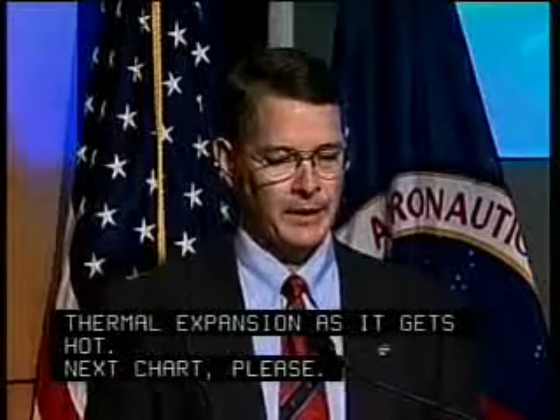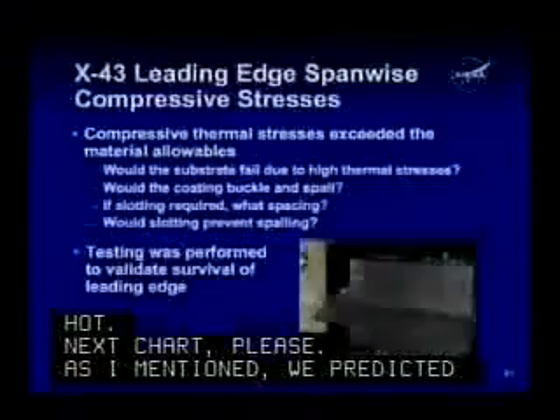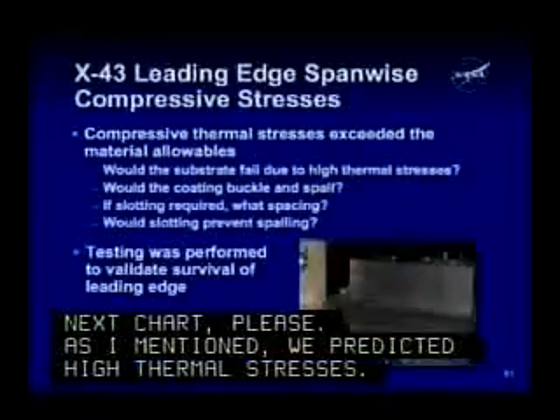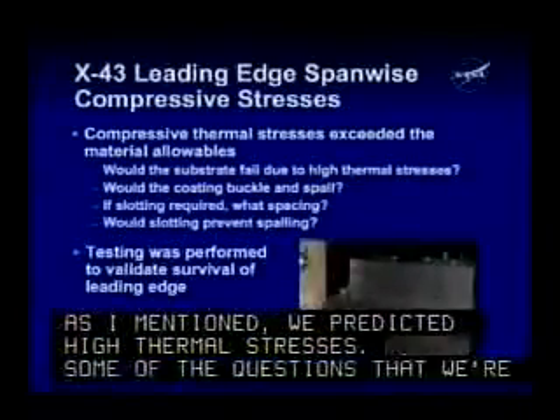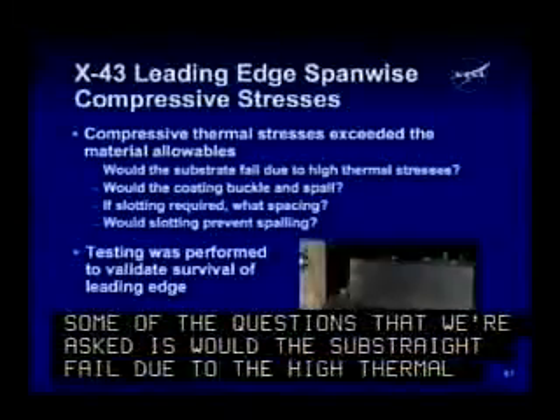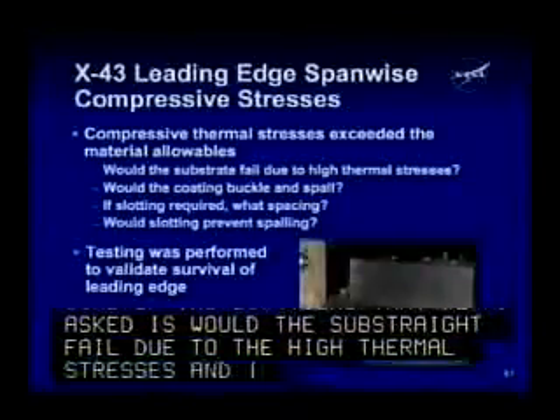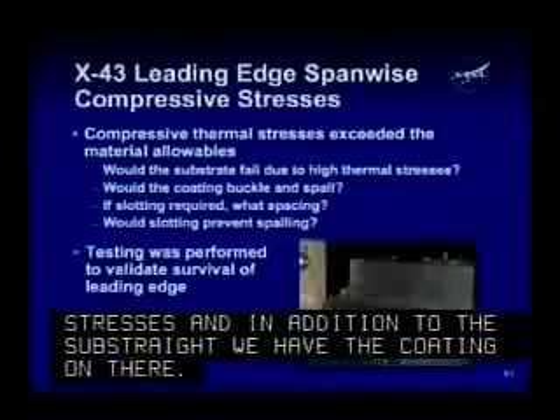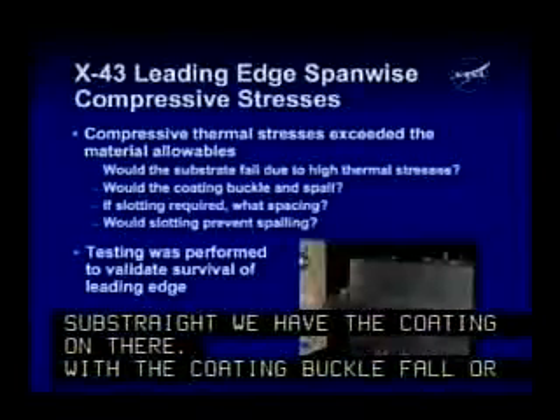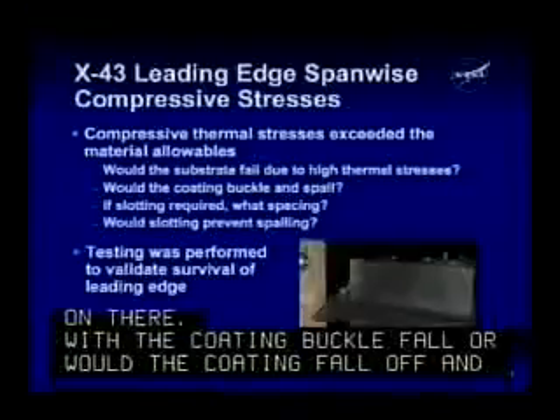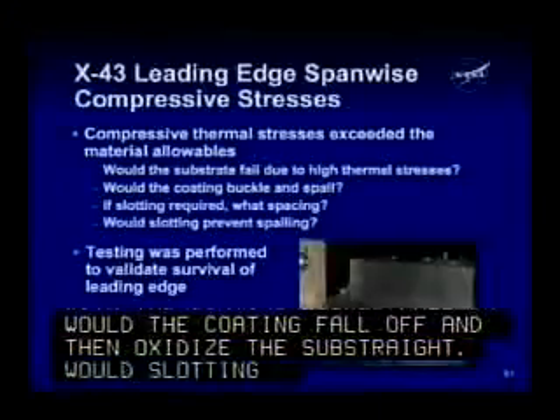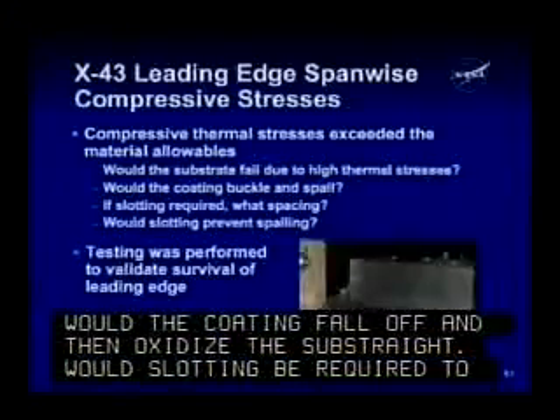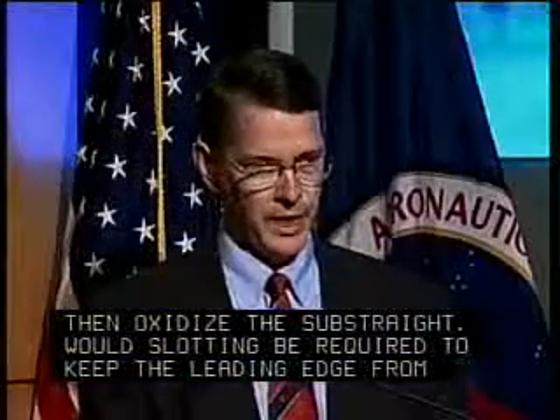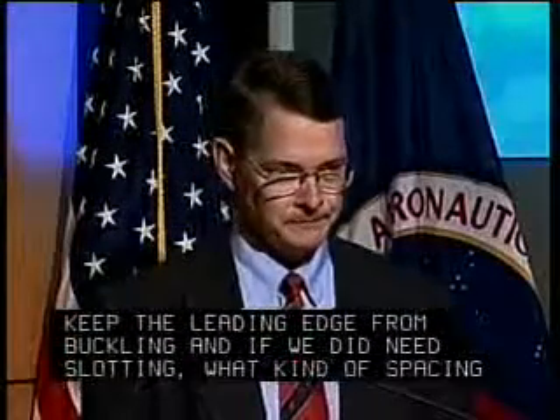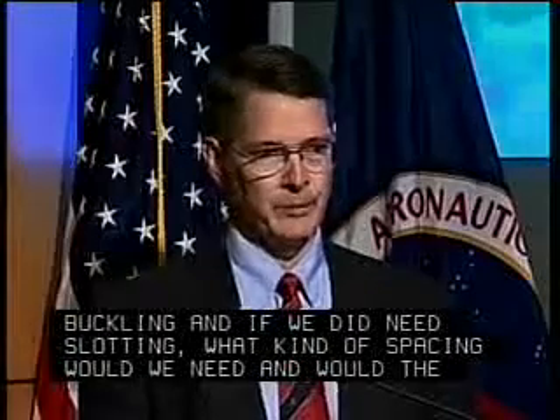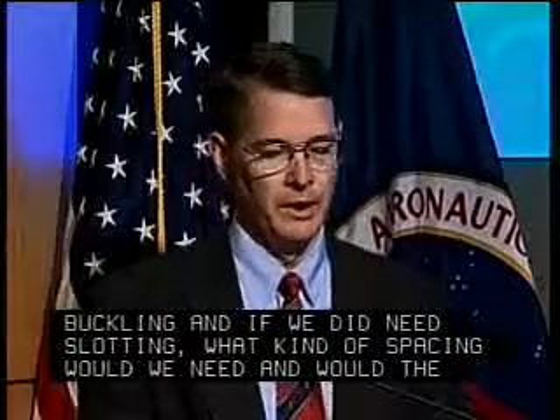Okay, as I mentioned, we predicted high thermal stresses. Some of the questions that were asked were, would the substrate fail due to these high thermal stresses? And then, in addition to the substrate, we've got the coating on there. Would the coating buckle and spall, or would the coating fall off and then oxidize the substrate? Would slotting be required to keep the leading edge from buckling? And if we did need slotting, what kind of spacing would we need? And then would the slotting prevent spalling of the coating?